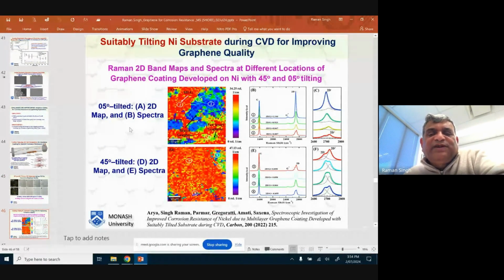We did Raman spectroscopy, and Raman imaging of the 2D peak very clearly shows that the 45-degree tilted sample had much more uniform graphene. You can see that all the spectra taken from different locations are similar, whereas the 5-degree tilted sample has spectra where at some locations you have very good multi-layer graphene, and at some locations you don't have very good quality graphene, and you will realize this in a sec.